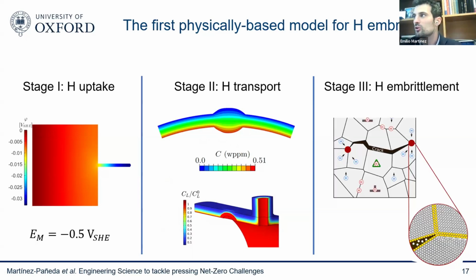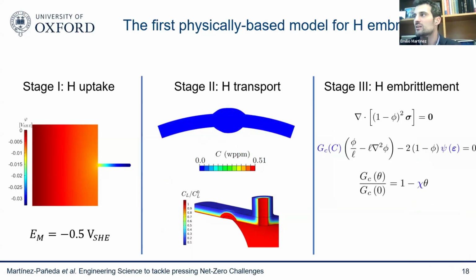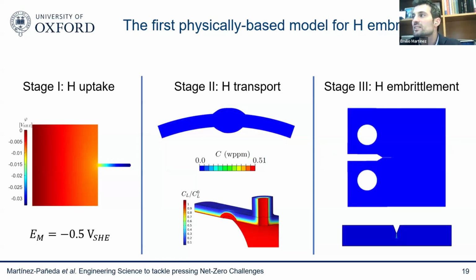And then finally is the embrittlement process. How does hydrogen trigger cracks? Again, we have equations for this. These are more on the mechanics side of things. And you can see here, basically, we capture the evolution. This is something called phase-field models of fracture. And you can capture how hydrogen basically reduces the toughness of your material. And you can connect this with atomistic simulations that tell you, without any fitting parameters, what is the reduction in fracture energy that you get from adding hydrogen atoms to your metallic system. And when you do that, basically, you can predict the nucleation and growth of cracks.